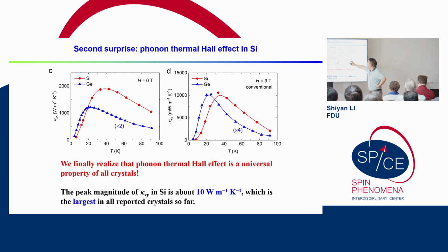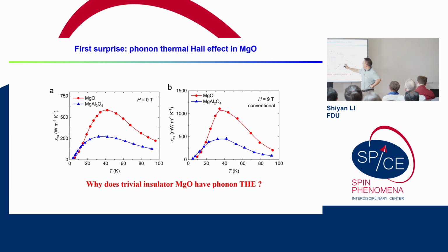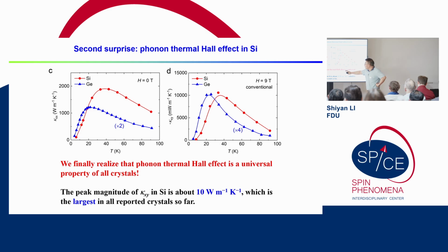Okay, then germanium is also germanium, and this MAO we measured later just to be sure that we have more single crystals all have this signal. So we finally realized that the phonon thermal Hall effect is a universal property of all crystals, right? On the shelf you have all kinds of signals. You take anyone, you measure it, you get the thermal Hall effect. And the peak magnitude of the kappa xy line in silicon is about 10 watts per meter per kelvin, which is the largest in all reported crystals so far.